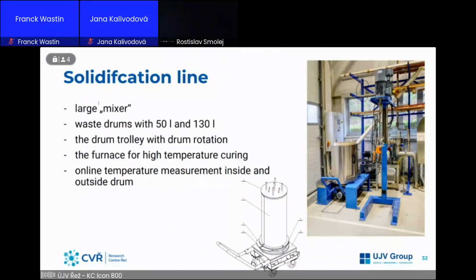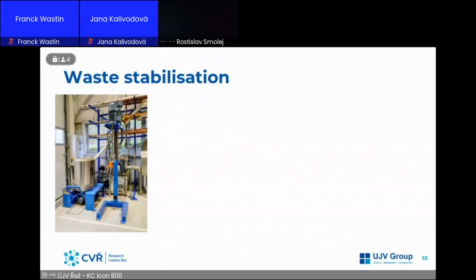Then we have our solidification line. Before, this was mainly put into the laboratory. Now we're going to the infrastructure. The solidification line is just a large mixer. Well, it's not just, but you know, we are using the waste drums with 50 liters and 130 liters volume. We also have the drum trolley, on the left-hand side, shown in the furnace for the high temperature curing. And we can have the online temperature measurement, to see how the curing goes inside the drum and how the temperature increases during the curing. And this is the end of the waste stabilization.